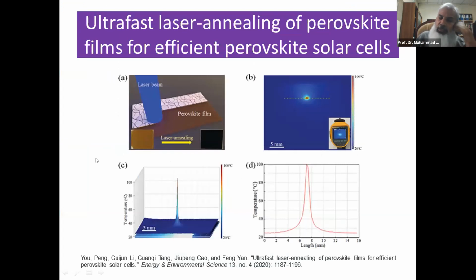Now that study was taking a long time. Recently, papers have been published on ultra-fast laser annealing, where a laser line beam is scanned over the film, and the temperature is optimized using a thermal imaging camera. Here you can see that annealing has been carried out using three different laser diodes and the conventional way, with laser diodes of 405 nanometer, 450 nanometer and 660 nanometer. You can see that the annealing carried out at 450 nanometer is better, showing a larger grain size.